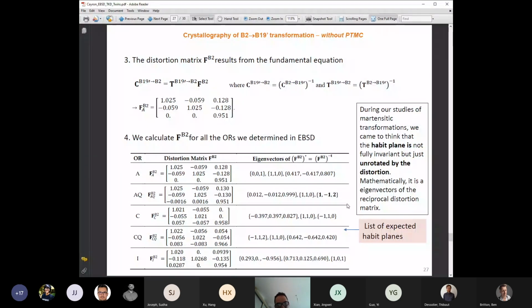And I finish with that, just to tell you that if I plot these predicted habit planes on the EBSD map, you see that it fits quite well with the experimental morphologies of the martensite.